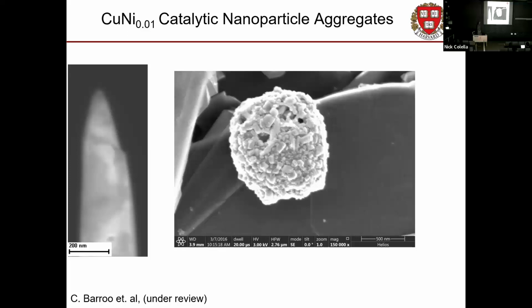It's supposed to be copper nickel, but it was only supposed to be 0.01 nickel, so 1% nickel at most. And these nanoparticles are real small. They're on the order of 10 nanometers around, which means they only contain a few thousand atoms, of which maybe 10 to 100 are supposed to be nickel. It's real hard to actually work out if any individual nanoparticle has any nickel in it. Just, depending on the size of the statistical distribution, there might be some with none.